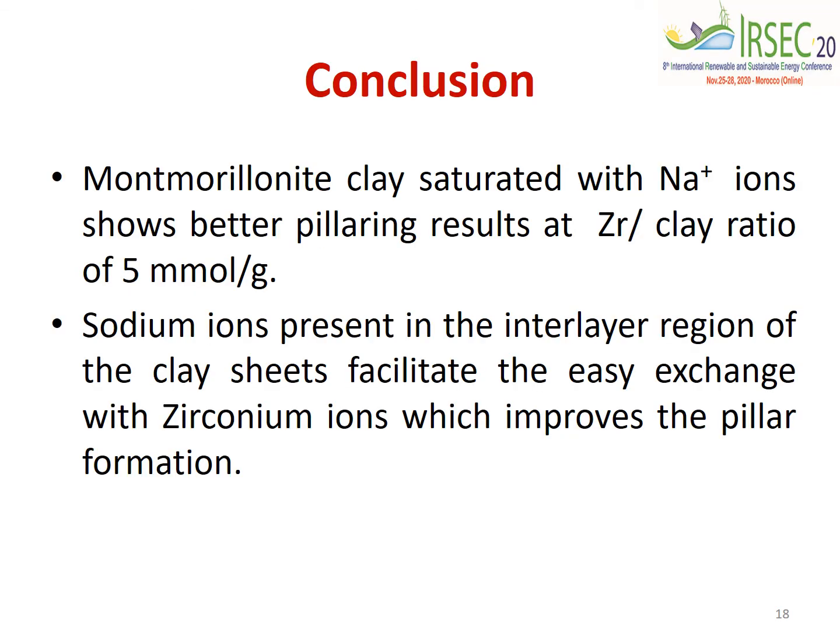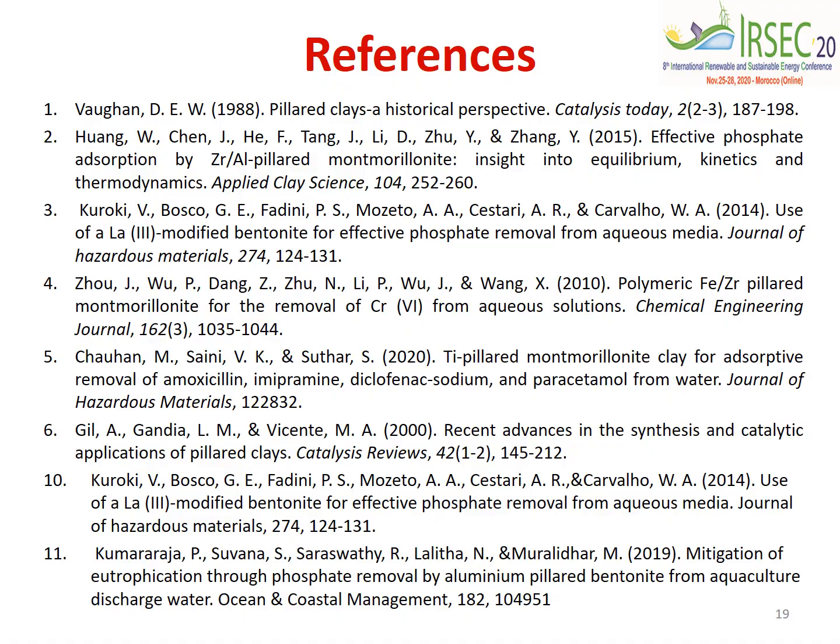Conclusion: montmorillonite clay saturated with sodium ions shows better pillaring results at a zirconium to clay ratio of 5 mmol per gram. Sodium ions present in the interlayer region of the clay sheet facilitate easy exchange with zirconium ions, which improves the pillar formation. These are the references.